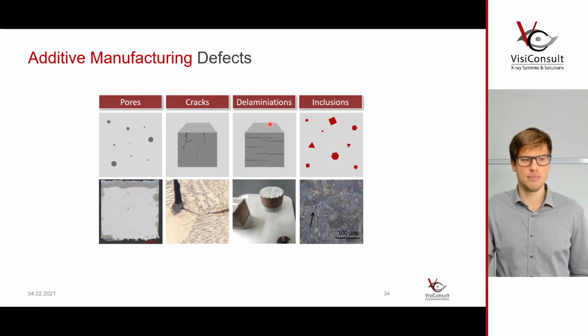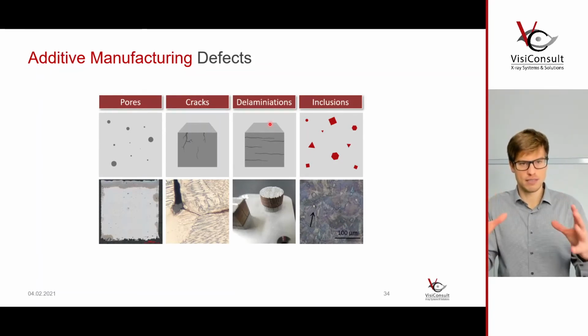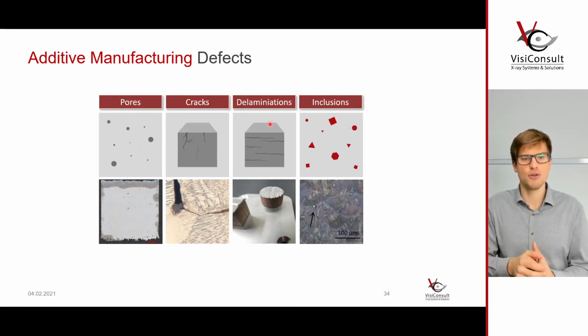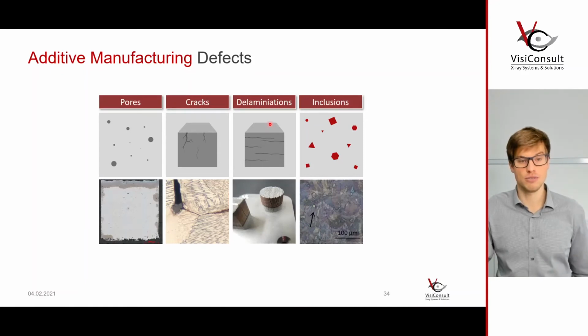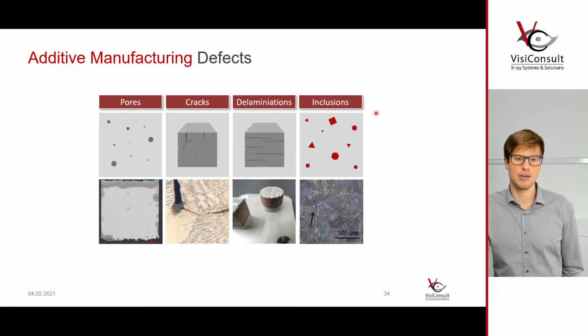And this is called delamination. So it can be a huge issue if your whole part looks good from the outside, and in the middle there's a complete layer that's not fused at all. This can lead to a severe part failure, and you will have to find a way to inspect it. And of course, inclusions also can happen, particles of higher densities brought in by the powder.